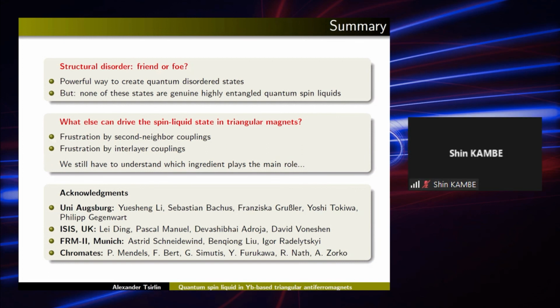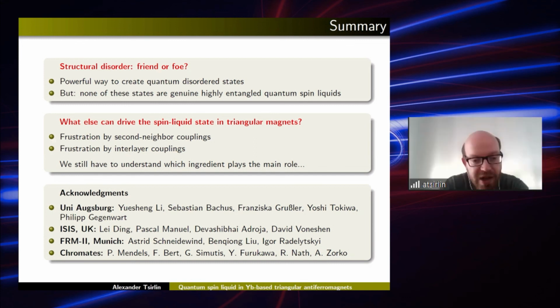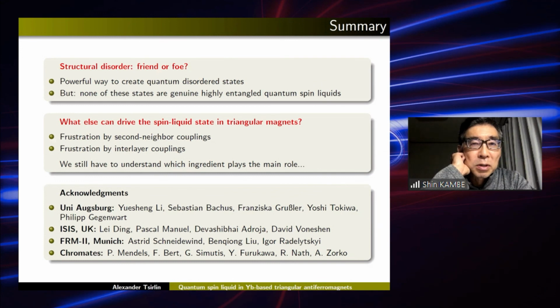I tried to show you that, well, getting the spin liquid states in the lab is possible. We do have some candidates. We do have systems with unusual excitations, but we still have to be quite careful in distinguishing the true origin of this behavior, because it can be the structural disorder. It can be different sorts of frustration, including the frustration by interlayer couplings, which is usually neglected in many theoretical studies, but that may be important in the real materials. And with this, let me thank the organizers for the opportunity to be here, at least remotely, and also thank you for your attention.